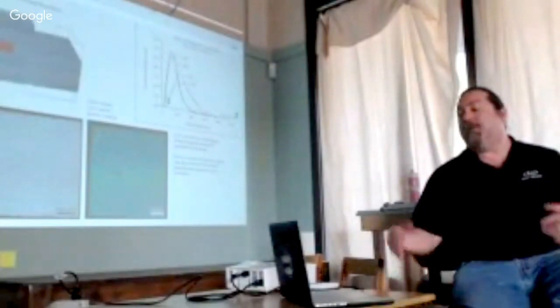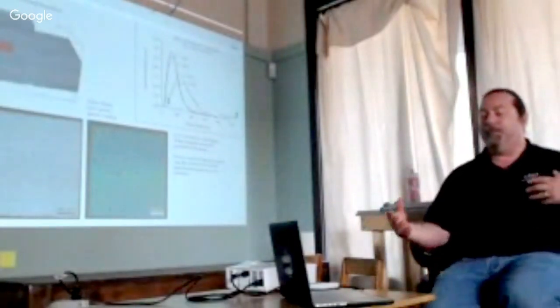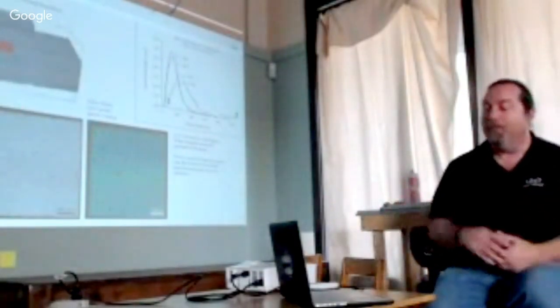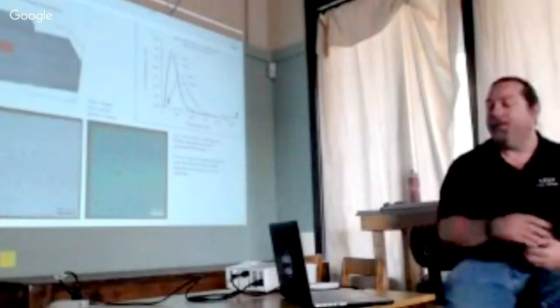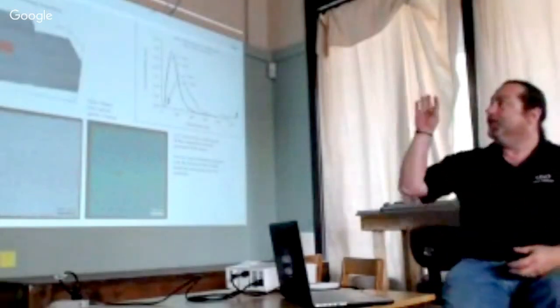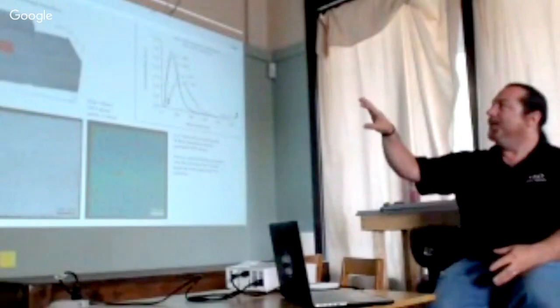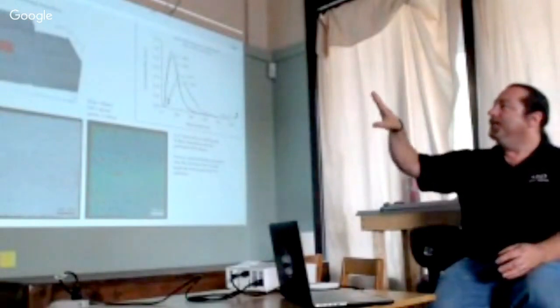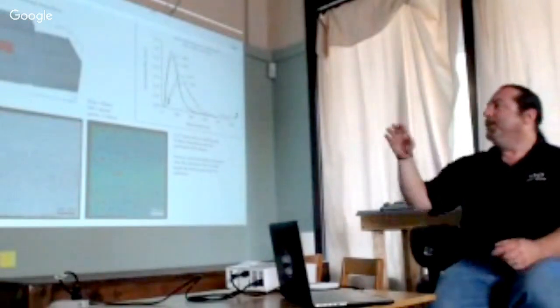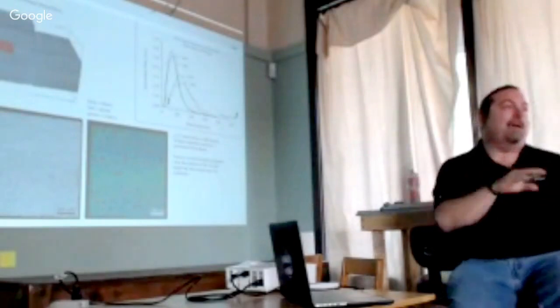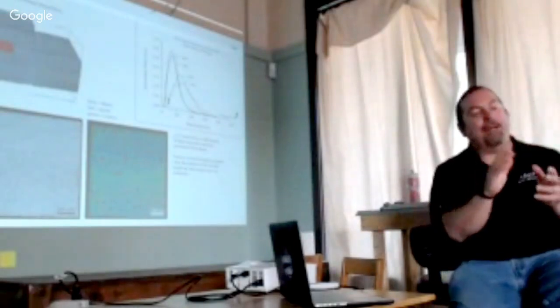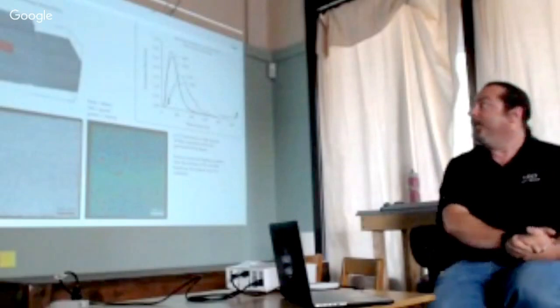So looking at the details of the fiber and looking at it under a microscope. The first was sort of just the optical microscope, looking at the inside of the bead versus the outer layers of the bead, you can see there's a difference in fiber alignment. The fibers are more highly aligned in the outer surface of the bead.